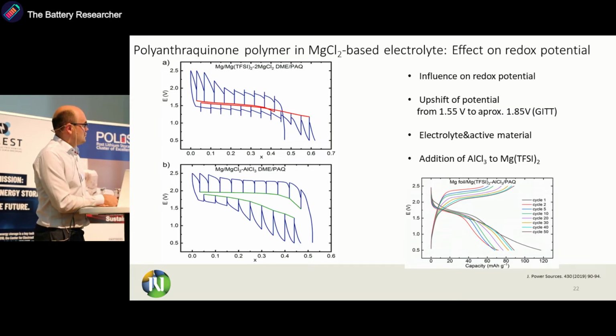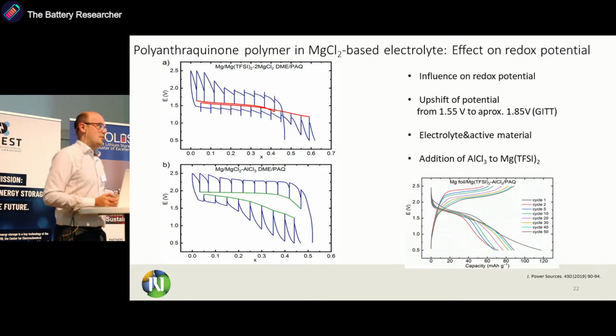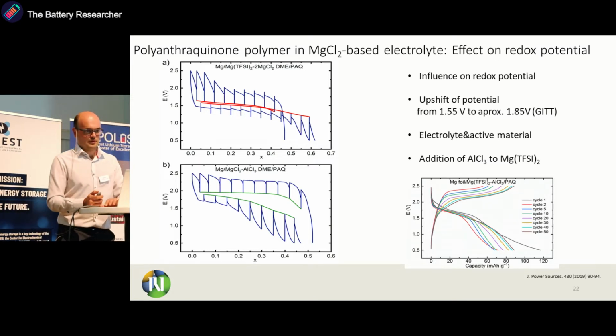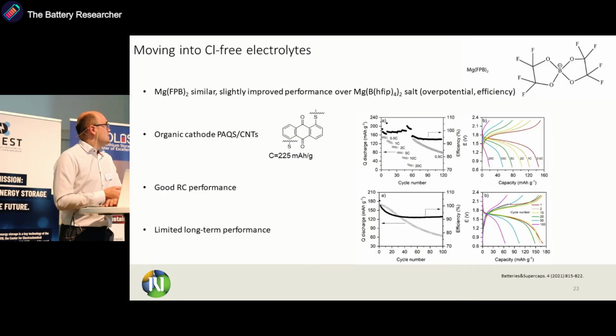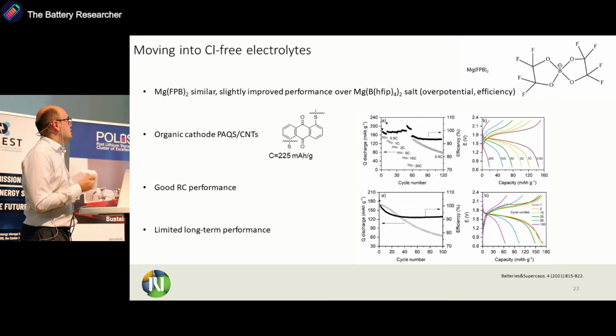And what we could observe is that also in this case, the redox potential upshifted. So it means that we have some interplay between our anthraquinone group and aluminum chloride, which moves our potential up by approximately 0.3 volts. So now we decided, with new electrolytes, to really move on with chloride-free electrolytes, because also the cell assembly is much easier.